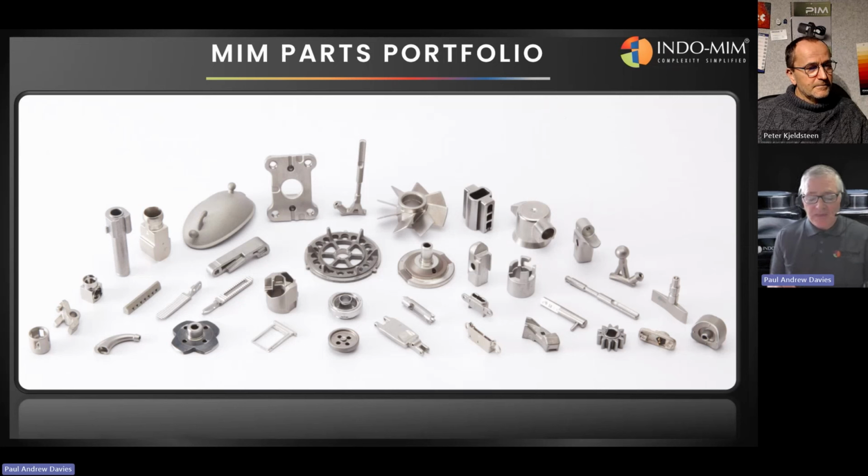There's a good synergy between additive manufacturing and metal injection molding. Of course, with the molding, you do need to make a mold, and that's important. So therefore, the cost of making that mold has to be taken into account in terms of the number of components. So additive manufacturing, which can produce components with, as you mentioned, a slightly higher degree of complexity, because you can have, of course, internal structures. Whereas metal injection molding, you are limited in terms of the three-dimensional capabilities and overhangs, but not internal structures per se.